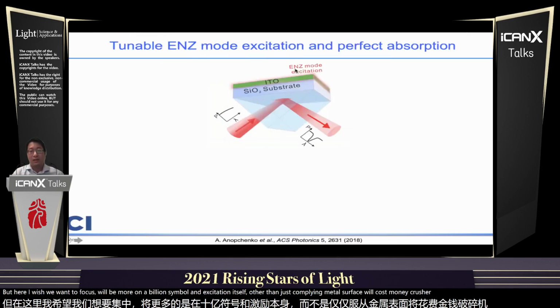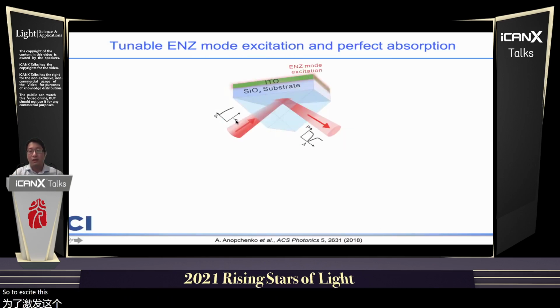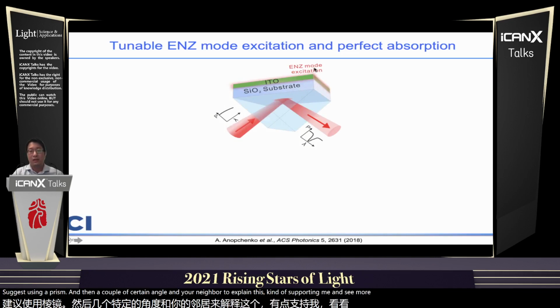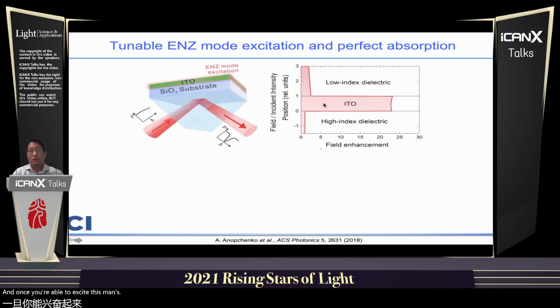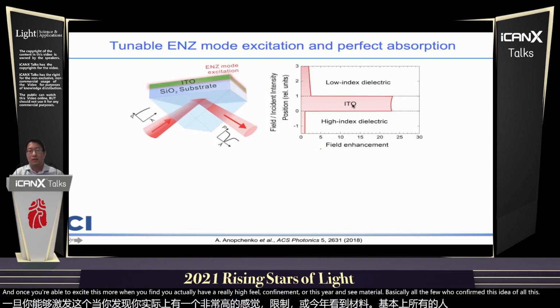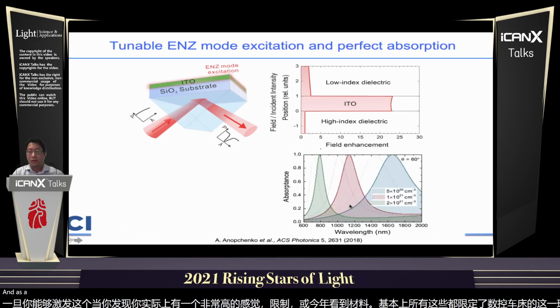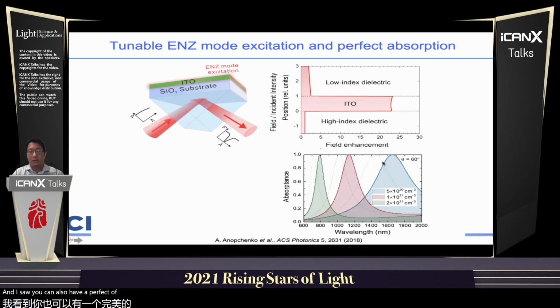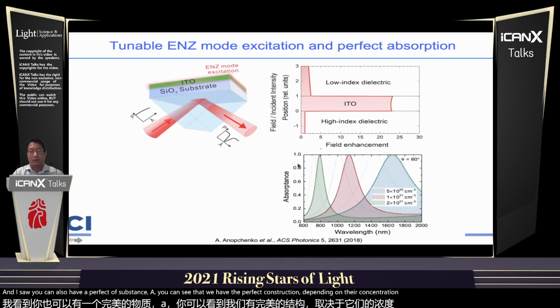To excite this kind of ENZ mode of the material, what you need is actually just a prism and then coupling at a certain angle, and you will be able to excite this so-called ENZ mode here. And once you are able to excite this mode, you find you have really high field confinement in this ENZ material. Basically, all the field will be confined in this ITO or ENZ layer here. And as a result, you can also have a perfect absorption. You can see that you have a perfect absorption depending on carrier concentration, and you can shift the absorption band here.